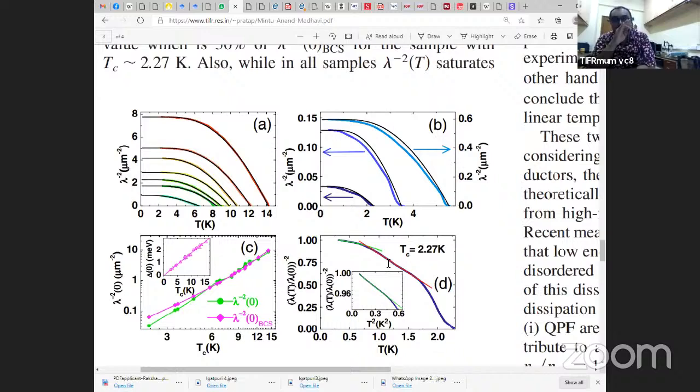Okay. So at high temperature, of course, as I told you, you will have anharmonic terms that will become important. That is horrendously difficult to calculate. But when you have nonlinear terms that dominate, the superfluid density precipitously drops and will go to zero. Fine. But the immediate question is, what is happening at low temperature? What I derived, if it is correct, then this should have been linear all the way up to T equal to 0. So this red line, which is the linear fit, should have extended, and at 0 my superfluid density should have gone here, out of the scale possibly.